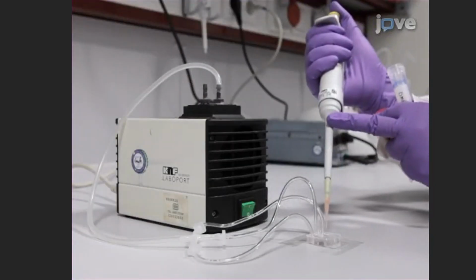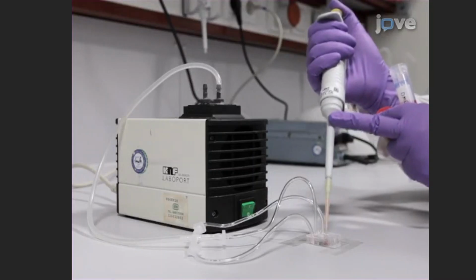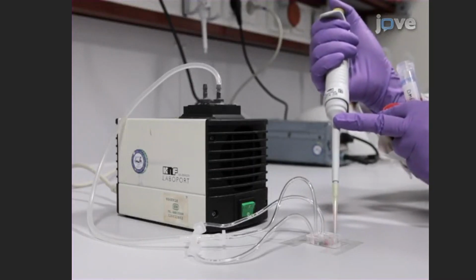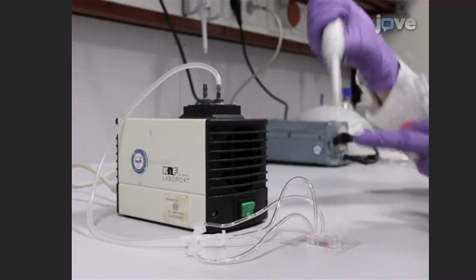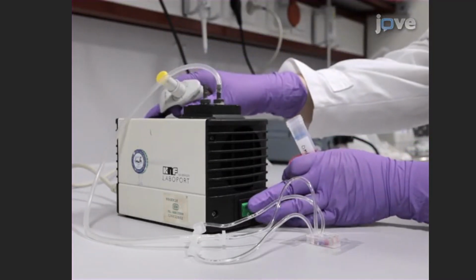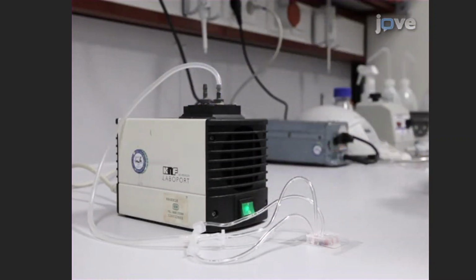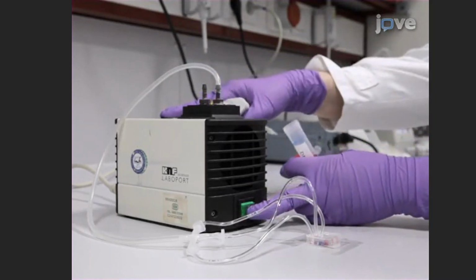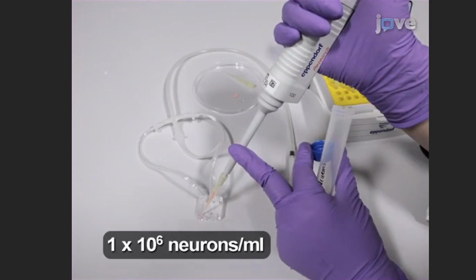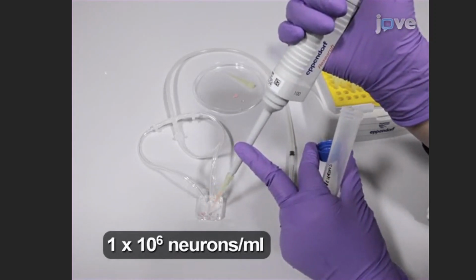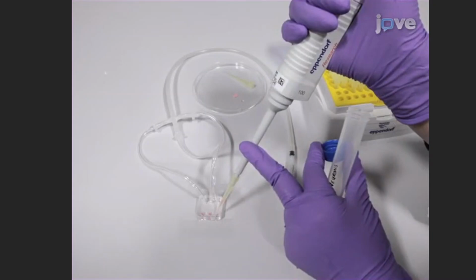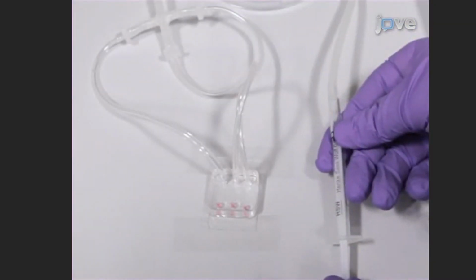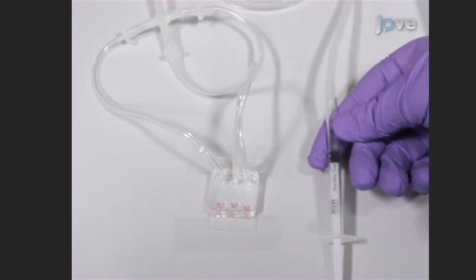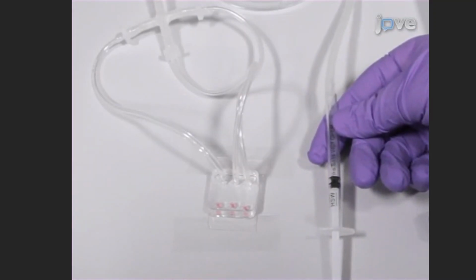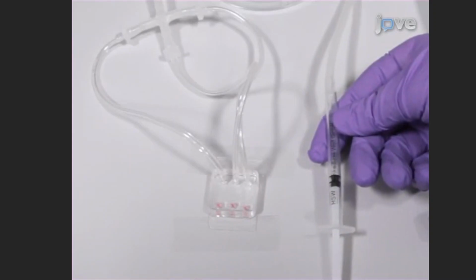In this procedure, prime the device with appropriate media by adding 20 microliters to each of the bottom 3 ports. Then, use parallel aspiration from the upper 3 ports to rapidly fill the microfluidic circuit with media. Add 20 microliters of a disaggregated cell suspension to each of the flanking bottom ports. Use a syringe to gently aspirate from the upper 3 ports. Complete neuron arraying typically requires 1 minute.